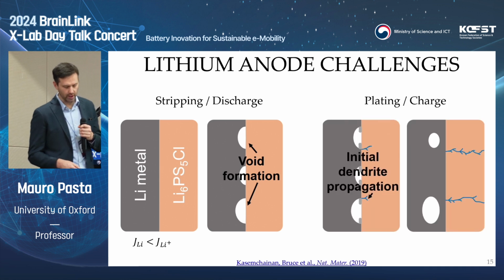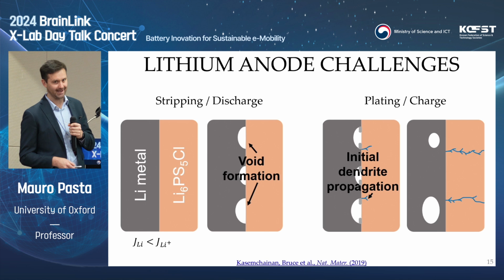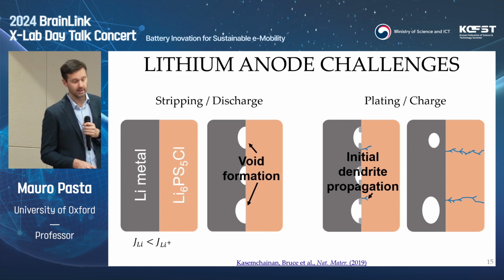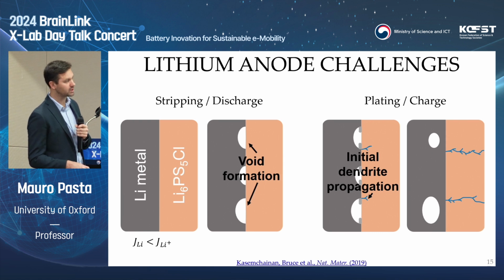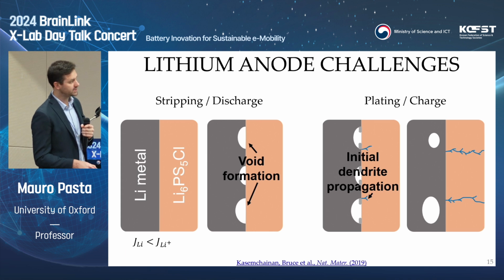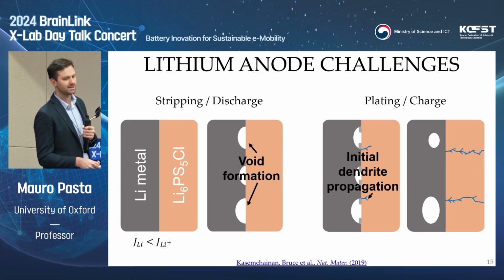On plating on charge, the challenges are mostly mechanical, in the sense that mechanical degradation leads to cracking of your solid electrolyte that is then backfilled by metallic lithium, resulting in short circuiting. These 2 phenomena are quite correlated, as if you increase voids, your current density is effectively increasing, and also this area provides a nice triple point, let's say, where you have access to space, ions, and electrons for mechanical degradation to occur. So you want to make sure that you prevent voids to start with, and then you can also tackle the problems occurring on plating or charge.